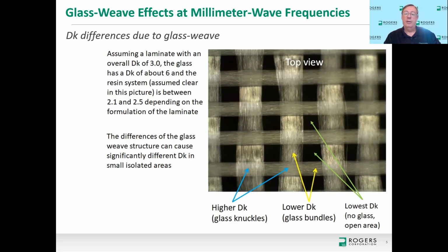Now you have resin on top, glass bundle, resin on the bottom, and that's going to be a lower Dk than where the blue arrows are pointing because you have less glass, and the glass is the higher Dk. And then, of course, the lowest Dk is going to be where the green arrows are pointing, and that's in the open areas where there is no glass. So in just a small area and looking at decay differences, you can see pretty remarkable differences of dielectric constant in very small areas due to this glass difference and how that glass reinforced the laminate.